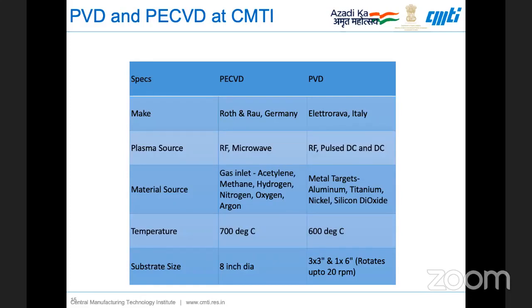For PECVD and PVD at CMTI, we have two pieces of equipment. The PECVD has RF and microwave, but essentially we use only RF here. We can use acetylene and methane, and the other gases are basically for dilution. It goes up to 700 degrees centigrade, and a substrate of 8 inches is possible to be coated.